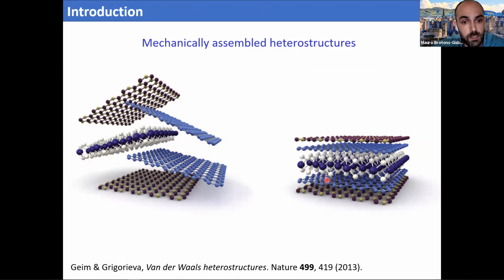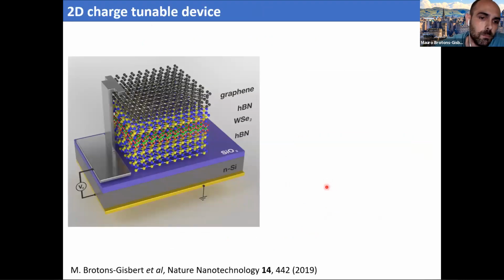So we decided to fabricate a device that looked like this, where we had our active layer, which was a monolayer tungsten selenide flake, encapsulated between two hexagonal boron nitride layers. Hexagonal boron nitride is a large bandgap insulator, okay? And then we finished the device by adding a few-layer graphene contact on top. And all this structure was deposited on top of a silicon and silicon dioxide substrate that was back contacted, and then the top and back contacts were connected.